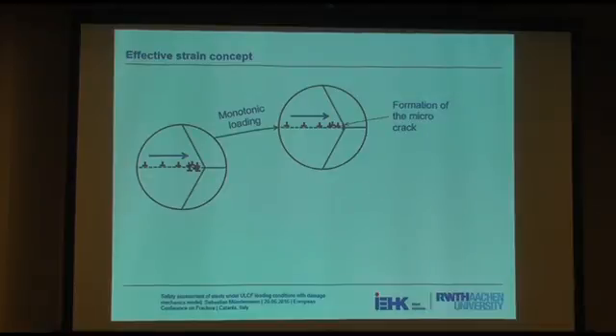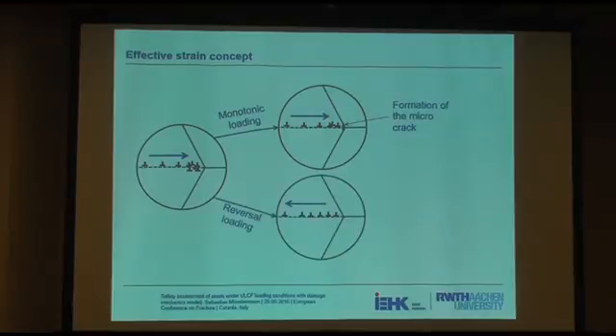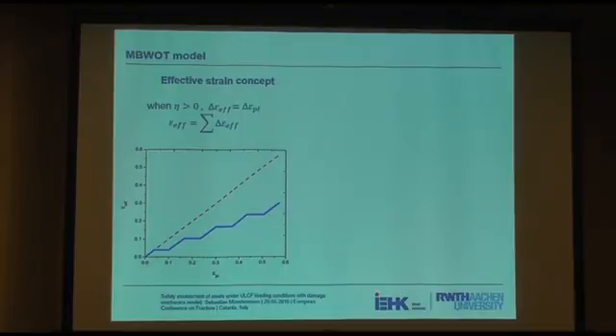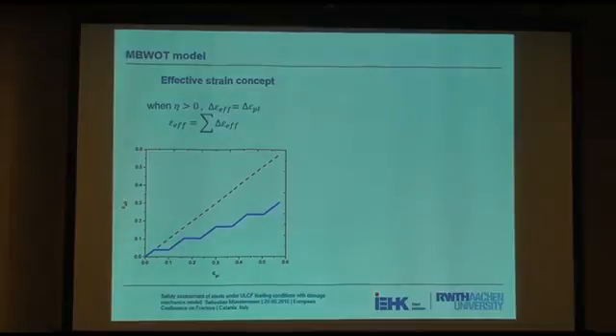Okay, the effective strain concept shall take into consideration that, in contrast to the monotonic loading, where all the dislocation slip will also contribute to nucleation of voids and formation of ductile damage, in reversal loading we can also have some kind of healing effect, because there's also a chance that the dislocations are slipping in the opposite direction. And of course, this has to be considered by the model.